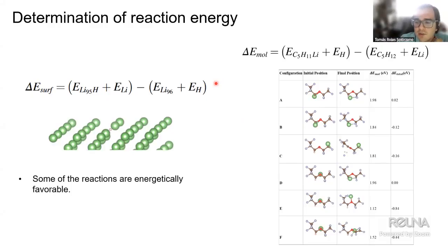And what those values tell us is that when we combine both of those deltas of energy, the total energy of the reaction for some of the cases, meaning for some of the hydrogens in the compound, gives us a negative value, meaning that some of them are energetically favorable. This allows us to predict not only that the reaction could happen, but if it happens, it will happen with which of the hydrogen atoms in the compound.